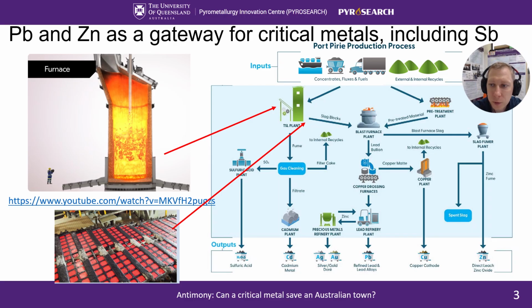The preferred option is to process all inputs in TSL, but the quantity of those materials accumulated on site is quite large, so the TSL alone does not have enough processing capacity. The blast furnace uses reduction chemical reactions to convert lead oxide into lead metal, while zinc remains in the slag. This process requires coke as a source of energy and reductant. Coke is produced from coal.